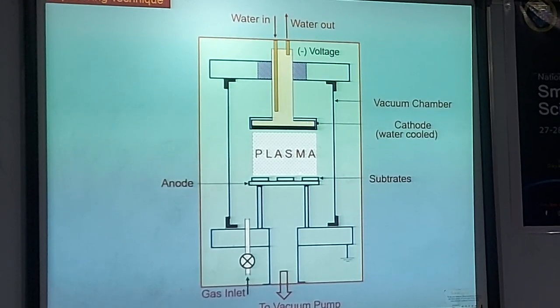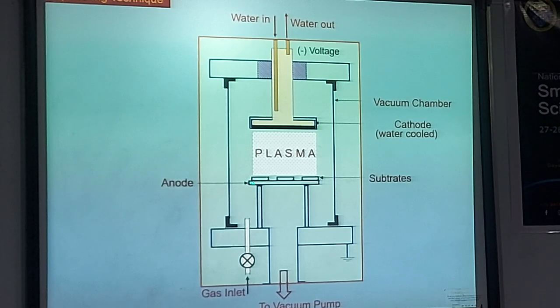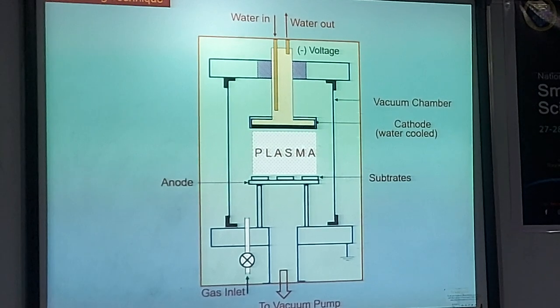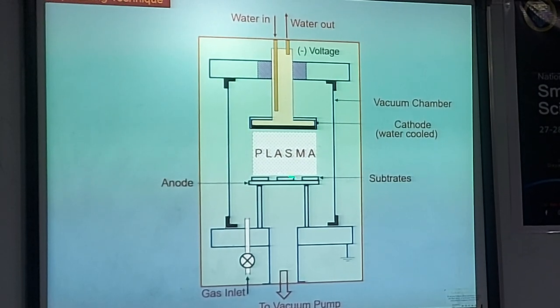And then we have the substrate on the lower side. We apply a potential between the target and the substrate, which is at a ground potential. Gas gets ionized. These ions go and hit the target and remove the target material, and the material gets deposited. This is a very sophisticated technique. Especially if you want to deposit expensive material like gold, platinum, things like that, there won't be any wastage of material. It also provides the flexibility to have good adhesion, etc.